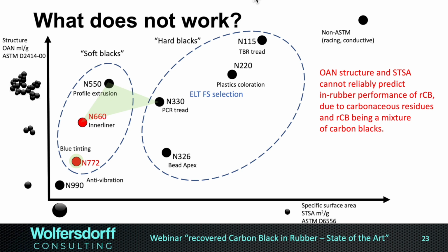So this is the performance landscape, or the carbon black landscape, of the oil absorption number over the statistical thickness surface area, which is the external surface area around the carbon black, not including the pores and the pore surface area. And we can see recovered carbon black typically would fall in this plot between a 550, 660 and a 330.